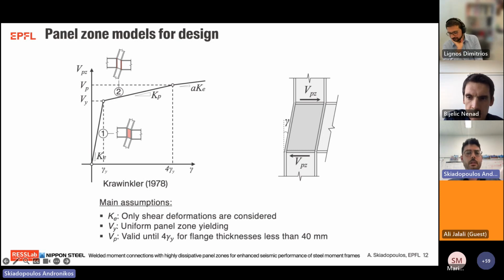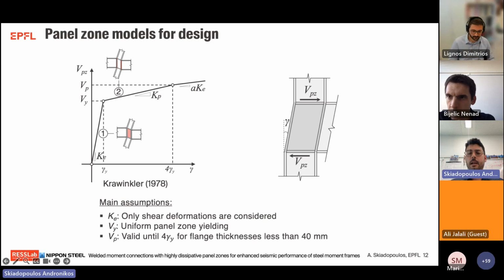The second branch is the post-yielding branch, and this was calibrated based on limited experimental data with column flanges with thicknesses less than 40 millimeters. Therefore, there is a limitation with regards to the column flange thickness. With regards to the third branch, the typical value of the post 4 gamma y panel zone stiffness equals 3% of the panel zone elastic stiffness.